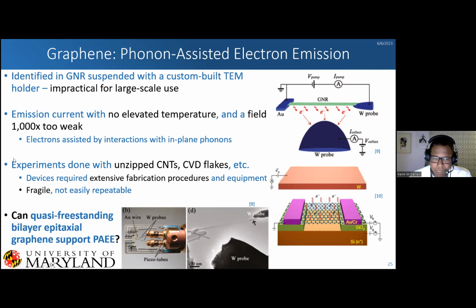People subsequently did experiments with unzipped carbon nanotubes and CVD flakes, all of these requiring very extensive fabrication procedures and equipment to actually suspend these flakes. It's very fragile and really not easily reproducible. And that's something we try to do in my lab: make sure that we're building things that have really high repeatability. So the idea was, if these are freestanding graphene flakes, and our graphene is quasi-freestanding, can we get the same kind of emission with very little energy put into the system?